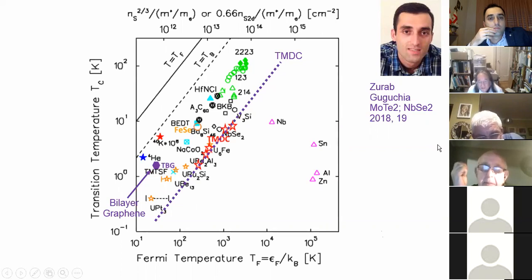And at least laser, even just a short transient time, can change the balance. And so if people find a clever way of changing the balance, even without using lasers, but for example, using radio RF or microwave or more easier excitation and stable over time, then you will be able to overcome this factor of 4 barriers. And then existing superconductors are already sufficient for being room temperature superconductors. Yes. So how to kill the competitor is, I think, one important route towards high room temperature. Recently, we also showed that by strain, you can increase TC of these type of compounds by a factor of 3. So Zurab is working by applying uniaxial pressure. And that is one way to control this balance between the two.